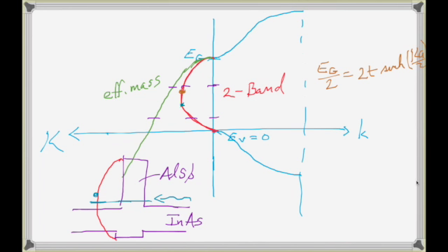If you think in terms of the conduction band and use your effective mass model, it will be utterly, completely wrong. Your kappas will be completely different because this is already wrapped around. It's already coming back to the valence band. Your parabolic model has just gone way out like this, and you'll get it totally wrong. So this is one of these systems where you have to go beyond your simple effective mass model to deal correctly with the tunneling.